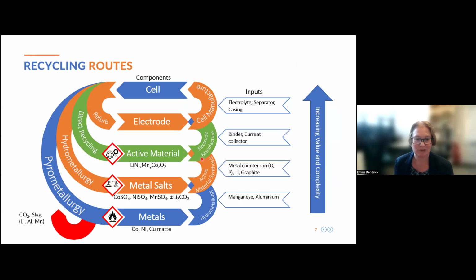So these are the typical recycling routes that are possible. We can take it through a pyrometallurgical process, recover the metals as an alloy, the lithium, aluminium, manganese in a light fraction or a slag, which we can recover from that. Or we can, as Martina has already spoken about, do some hydrometallurgical processes to recover the salts and then remanufacture the active material components from this. Or we can directly recover the active material components and try and reprocess them back into an electrode and back into a cell. And this is very much what we're trying to do in a lot of our work.